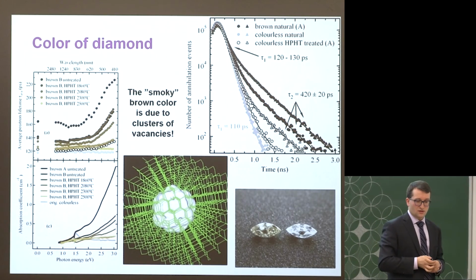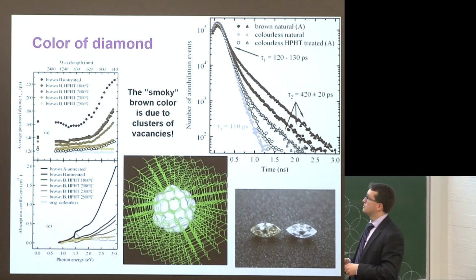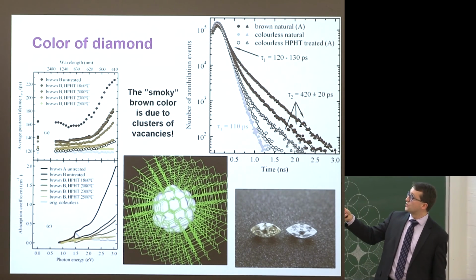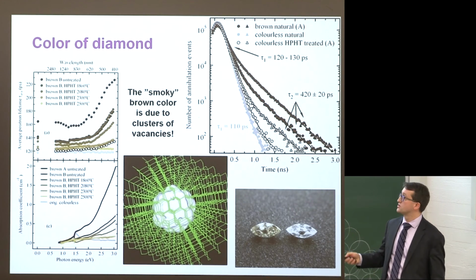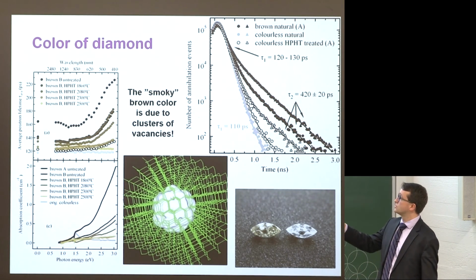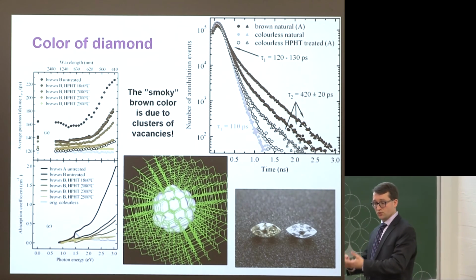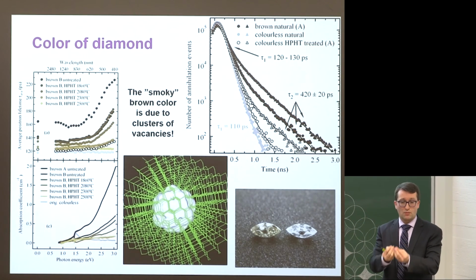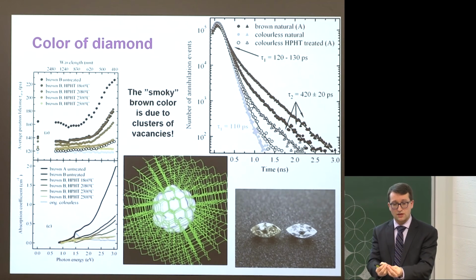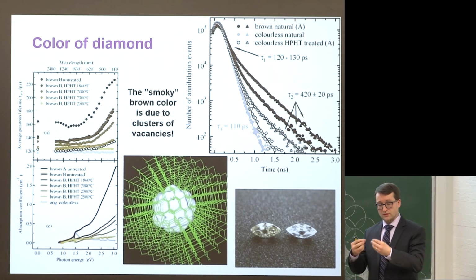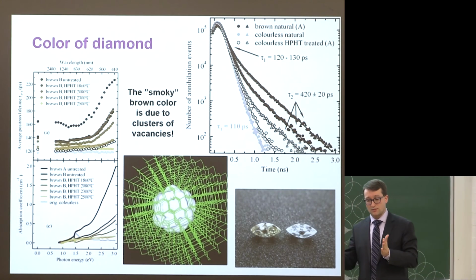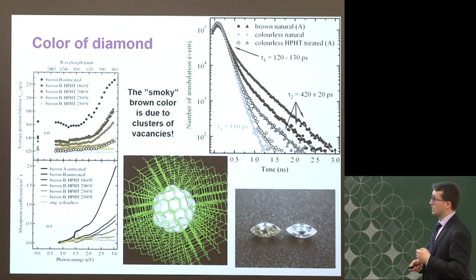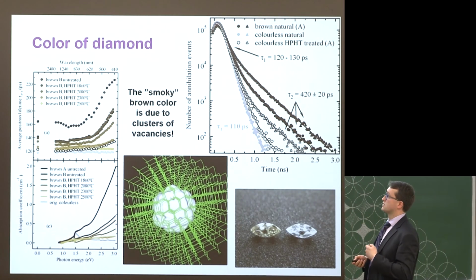physicists, in addition to liking to show oscillations, the other thing physicists like to show is decays. So this is now an example of what the experimental data we obtain might look like. This is the number of annihilations as a function of time. So this represents somehow the lifetime of the positrons inside the crystalline sample. We measure how much the positron actually likes to stay there before it's annihilated with the electrons. And if you have these vacancy type defects or missing atoms, this lifetime becomes longer and longer, and using that as one of the quantities, you can tell how big the vacancy defects in question are.